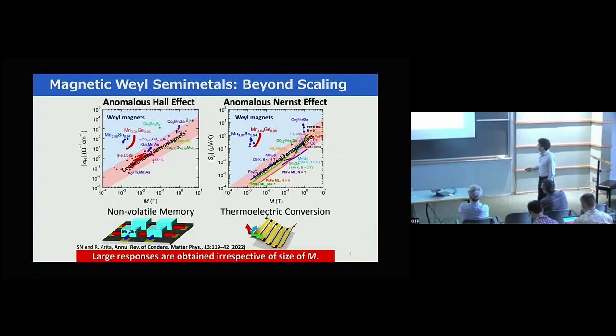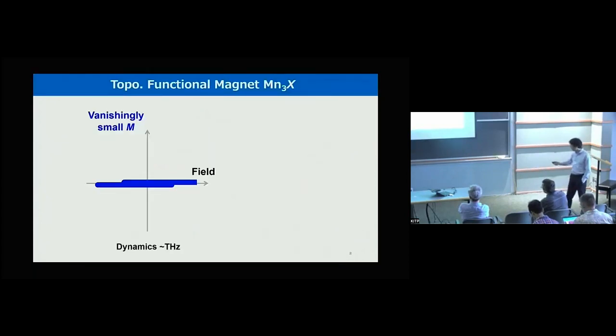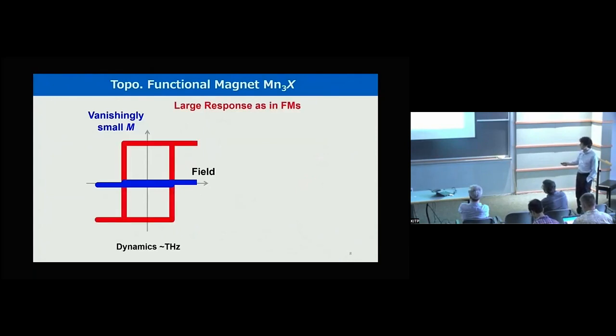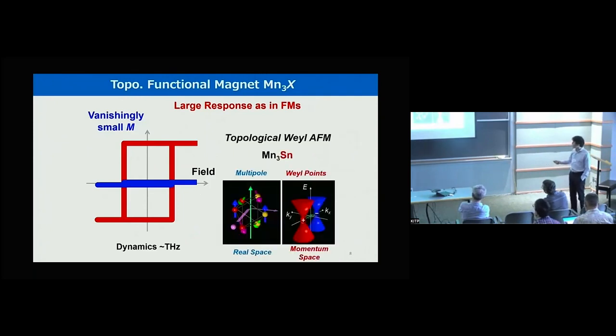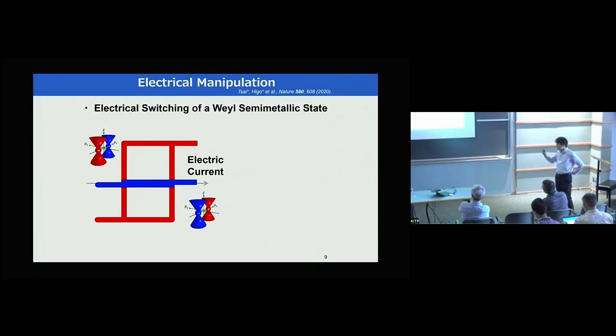One of the prototypical systems is Mn3X. This is the material I'm going to talk about. We found a very large response as if it were a ferromagnet, despite the fact that it doesn't carry magnetization. And two ingredients are very important for this system: the octupole, a cluster-type octupole in real space, and the other one is the Weyl point in momentum space.